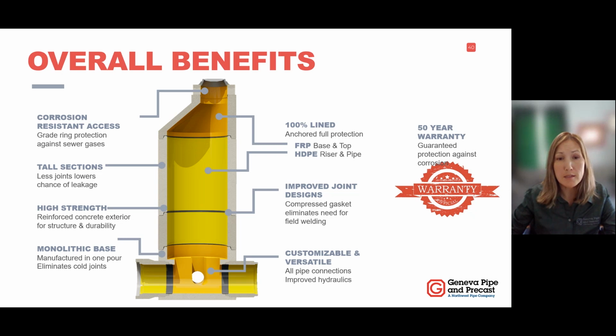So as you can see, the base is lined, but it's lined with FRP, or fiber reinforced polymer. It is not easy to line the complex configuration of the base because you have all these turns and troughs and channels. And so we line it with FRP. And then we have risers that are lined with HDPE. You saw in the previous picture when I was talking about the pipe, it's lined with a perfect liner, HDPE liner. We have lots of anchors in it.